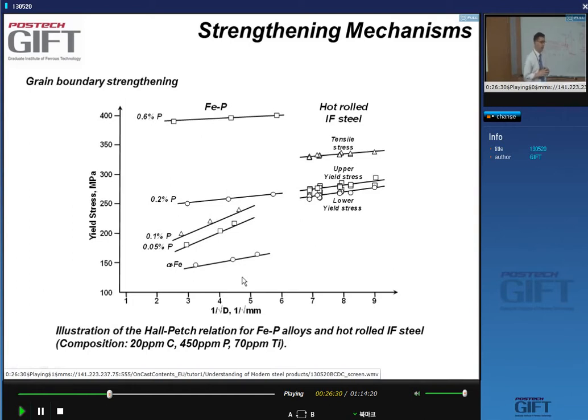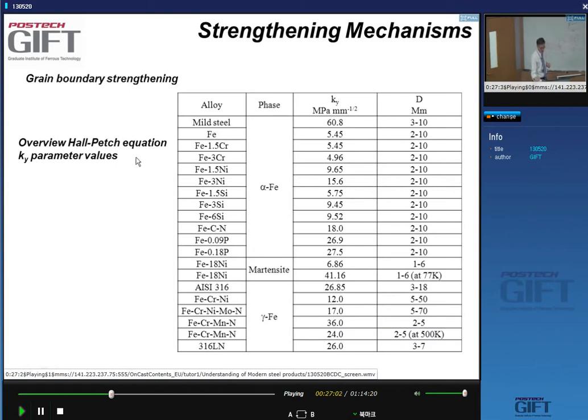So the message here is, when you are trying to evaluate or calculate the Hall-Petch effect, always watch out for what the composition of your alloy is, because you cannot just take literature data and apply it. There's a lot of literature data. Here's an example of Hall-Petch KY parameters for different alloys: alpha iron, mainly ferritic alloys, martensitic alloys, austenitic alloys, and you can see that in particular for the ferrite, you see a very wide variation.